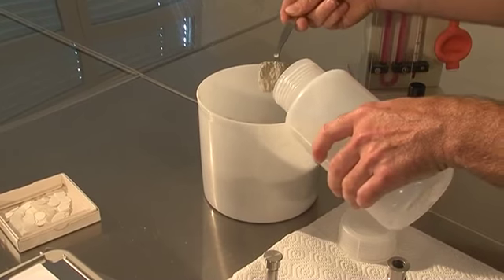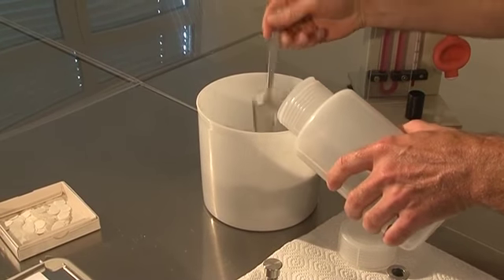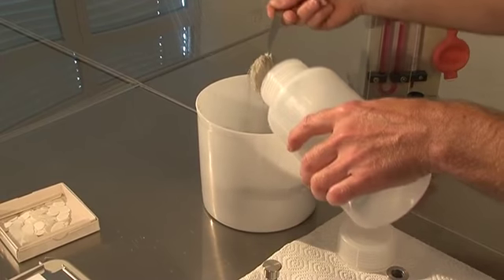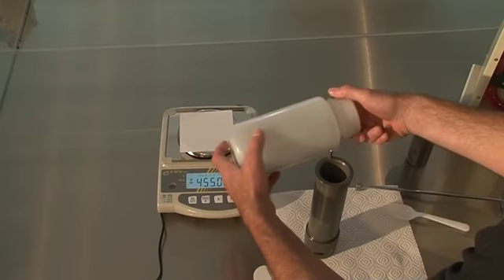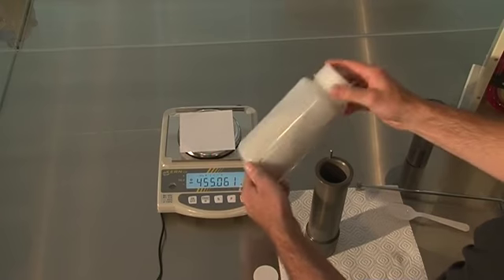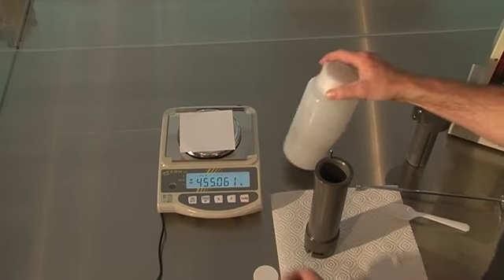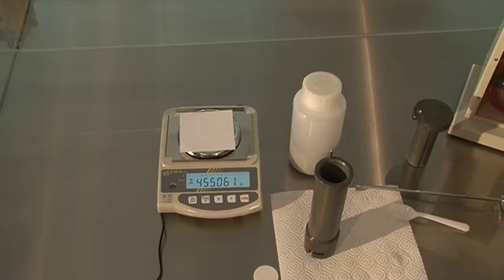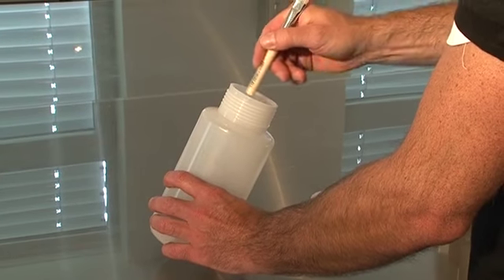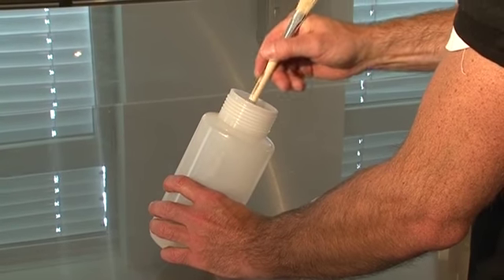A sufficient quantity of the cement to be tested is filled into a jar with a screw lid and shaken vigorously for 2 minutes to dissolve any agglomerates. Then leave the sample to stand for 2 minutes. Subsequently, distribute the fine particles with a dry, clean rod.